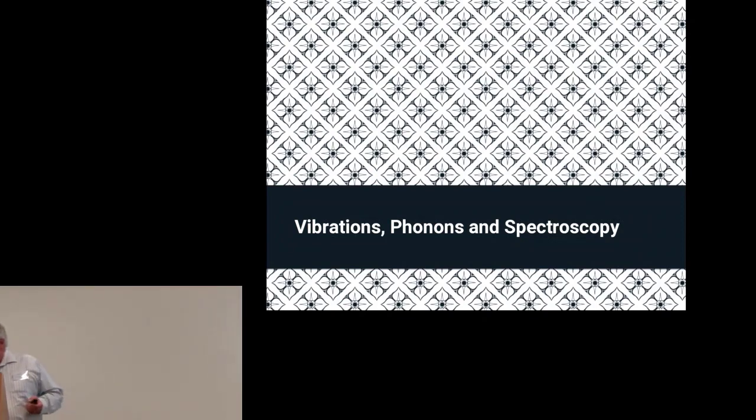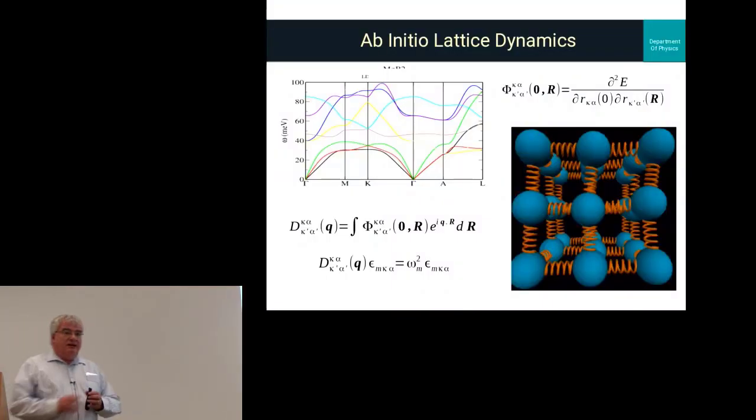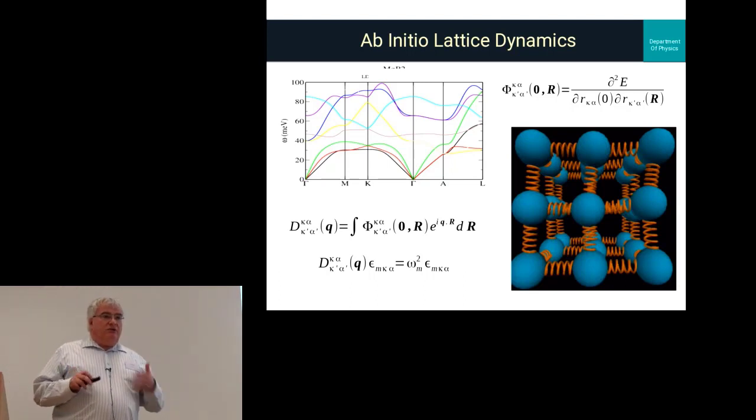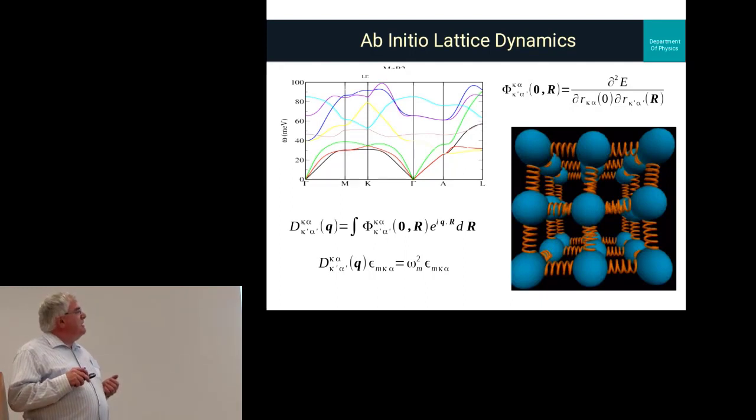A word about phonons. One of the lovely things about having high-throughput DFT calculations is that we can calculate the phonons by a complete parameterization of essentially a ball and spring model of the crystal. The model is misleading only in that the springs connect not just neighbor atoms as shown in the picture, but they connect all pairs of atoms in our crystal.